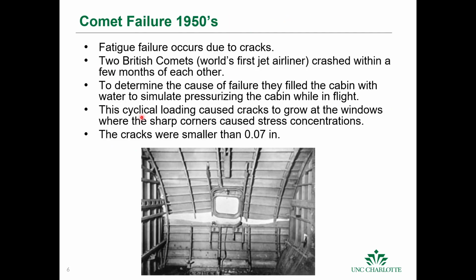Fatigue occurs because of cracks. There were two British Comets, the first jetliner, and they crashed within a few months of each other. They took the debris and reconstructed a test to determine what was causing the failure. They filled the fuselage with water and pressurized the cabin to simulate the stresses that would occur in flight. They found that the cyclical loading caused cracks to grow around the windows, and these cracks were less than 70 thousandths of an inch. So even very small cracks in the structure, when subjected to dynamic loads, can cause catastrophic failure.